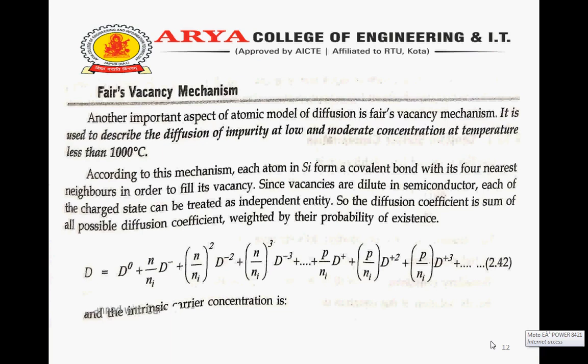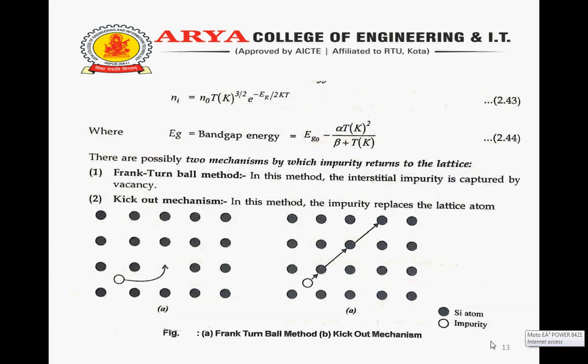The intrinsic carrier concentration is Ni equal to N naught T to the power 3 by 2 e to the power minus Eg upon 2kT, where Eg is equal to Eg0 minus alpha T squared upon beta plus T. There are two possible mechanisms by which impurity returns to the lattice. First is Frank-Turnbull method. In this method, the interstitial impurity is captured by a vacancy. Second is kick-out mechanism. In this method, the impurity replaces the lattice atom. Thank you.